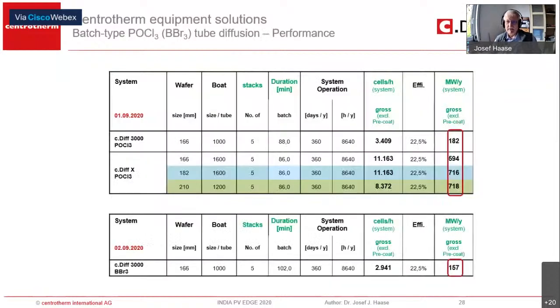When we look at the throughput, it's even more amazing. When the old machine had about 182 megawatt, then we have, with the DIFF-X, about 600 to 700 megawatt throughput in one machine. And this is all for the POCL diffusion. If we look at the boron diffusion, there's still only the 5-tube system. We have developed a process for the 10-tube system. We had so far no request from any customer for these wafer sizes. Next, please.